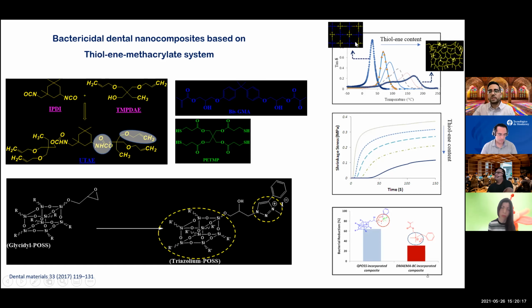The first one is related to pure thiol-ene, and the last one is related to the samples with lower amounts of thiol-ene. It mentions that the thiol-ene system is really nice regarding the homogeneous system. The next one is related to shrinkage stress, and we can decrease the shrinkage stress by increasing the thiol content.